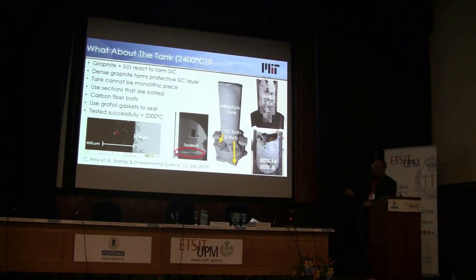done a few thermal cycles of these materials to see that it's not like the silicon carbide comes off and then it starts consuming more. That doesn't seem to happen. So whatever the silicon carbide layer is, it's rather adherent. And we've done tests with a number of different grades of graphite, so it really depends on the pore size, the amount of porosity, and things like that. Where this matters most is in the tank, because you'd like to use the cheapest form of graphite you can that still works. One of my students is looking into that carefully.